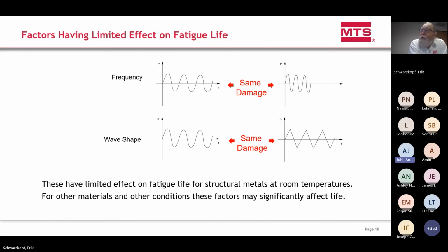There are some things that don't really affect the S-N curve much. Frequency is one of those, at least at room temperature — you can run this test at a very high frequency or a relatively low frequency and get the same results. When you start introducing time-dependent effects like creep or corrosion, all bets are off, since the amount of time spent under that environment will change the life.